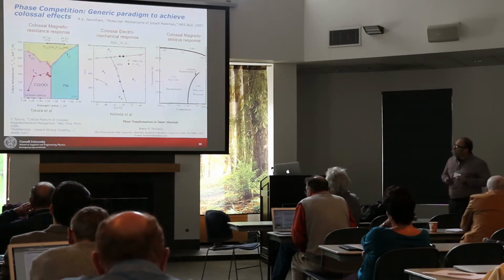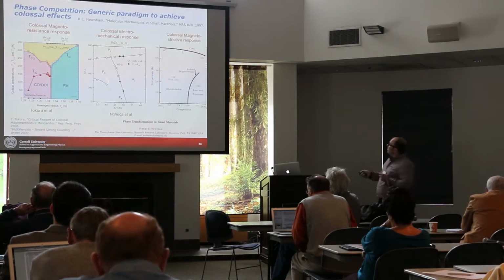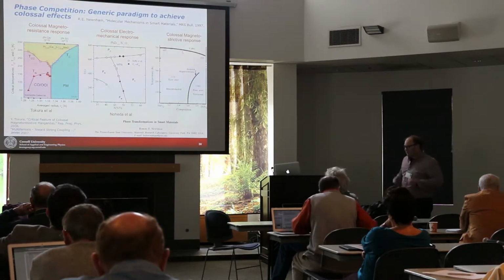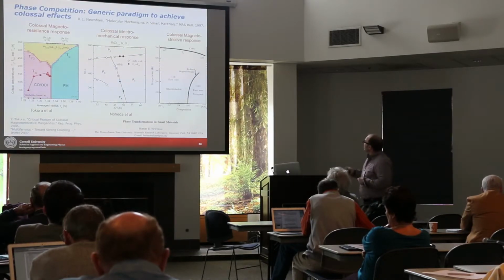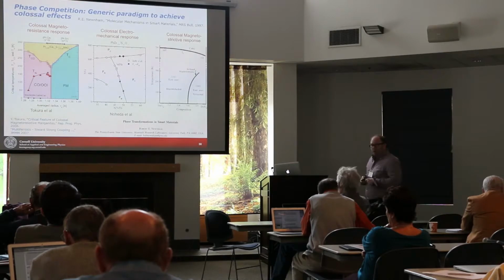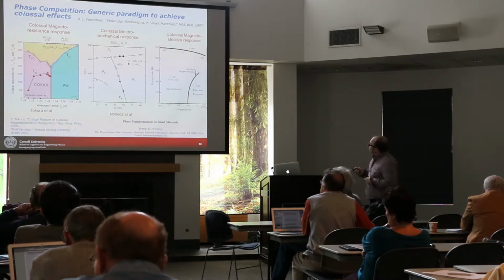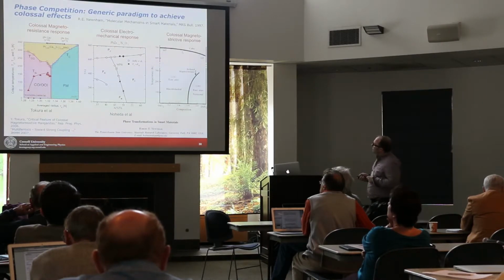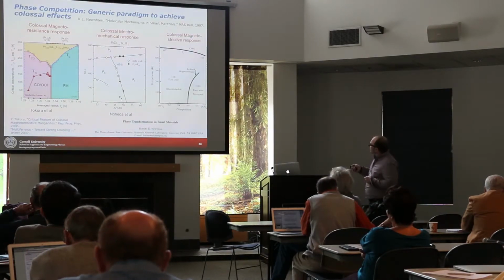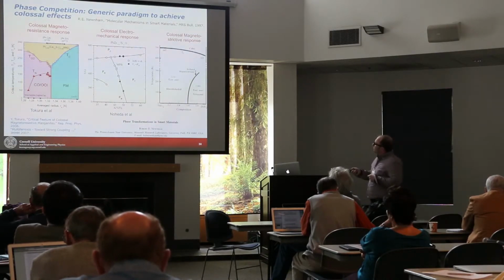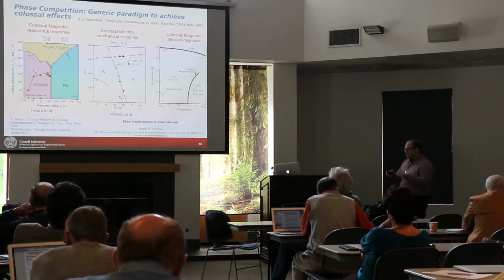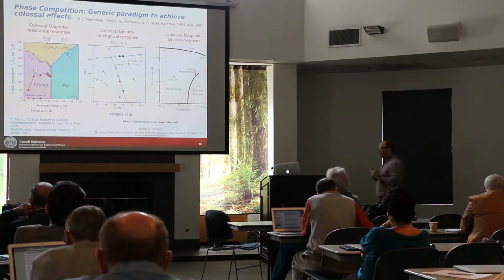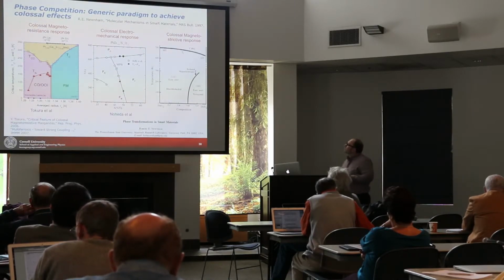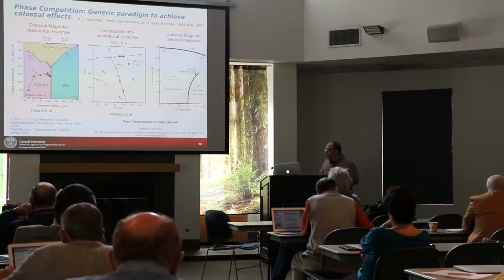This one displays a colossal magnetoresistive response. This material here displays what we call a colossal electromechanical response. It's the best known piezoelectric material that exists. And this one is our best known colossal magnetostrictive material. The underlying universality of all of these is that these large responses occur right in the vicinity of these vertical phase boundaries shown here. So the idea is that one tunes to a phase boundary, and in the vicinity of these phase boundaries, we have these large responses. So can we tune to a boundary and take advantage of these various competing phases to produce large and colossal responses?